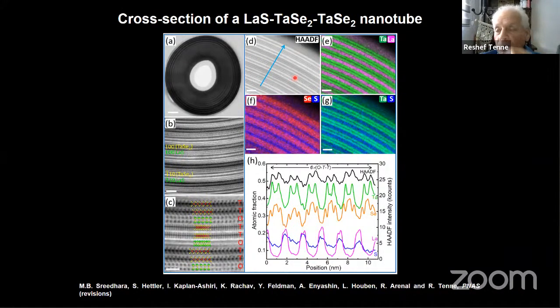And because there is not enough sulfur, we get multiple layers of tantalum selenide per one layer of lanthanum sulfide. And that is seen beautifully here. You see the structure, you can see each and every atom in this structure. You can analyze it chemically by EDS, high resolution EDS, and you can understand the chemistry via the high resolution TEM and related studies.